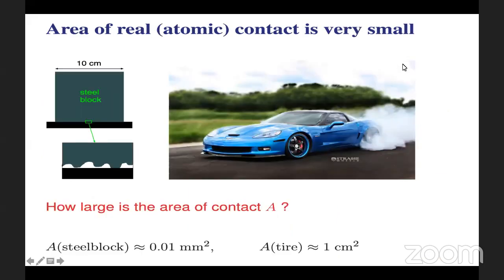If you take two steel blocks, because of surface roughness, you will see that the area of real contact is very small. If you calculate the area of real contact for these steel blocks, which are 10 centimeters wide, the area of real contact will be approximately 0.01 square millimeters. This is for elastically hard solids. But if you take a smooth rubber, for example in a tire application, you will see that the area of contact will be approximately 1 square centimeter.